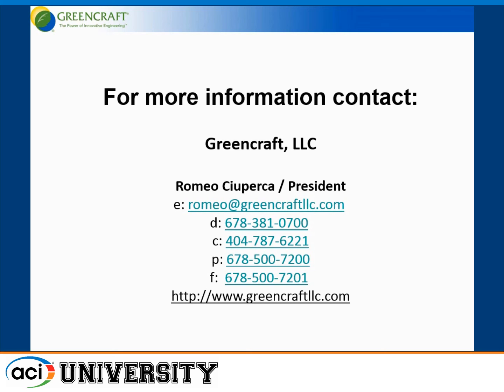I really appreciate you bringing that up. In this case, the initial mixing water is more than sufficient to hydrate all cement. So by retaining that moisture, you're not going to need to moisture cure in a conventional way, put moisture back into the system. So that's a non-issue in this case. Thank you.